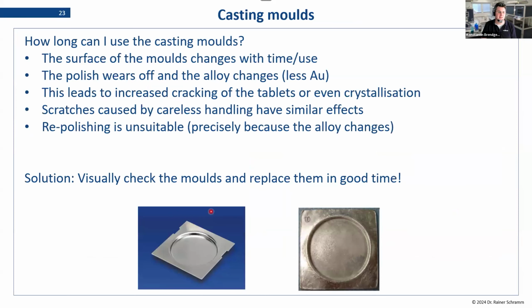Casting molds, yeah, very careful with those. As I mentioned before, the gold content changes, so we have to recycle them at one point. We cannot repolish them, because repolishing would make the surface nice again, but it would not get the gold back in. So recycling is a must here.